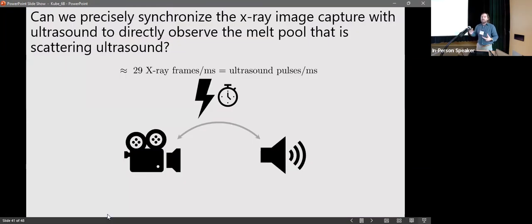So we're using this ultrasound in a pitch catch configuration, so 1 transmitter, 1 receiver, and we're looking at the scattering from the melt pool boundary. So we synchronize everything with the X-ray. So we have a picture of the X-ray image that corresponds exactly with the recorded signal at that instant. And so we're collecting at about 29 kilohertz, or 29 ultrasound waveforms per millisecond, so pretty fast.